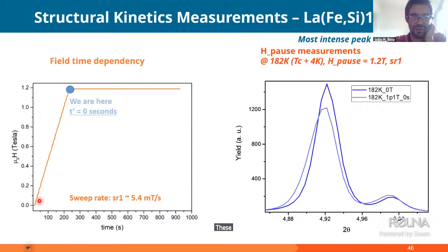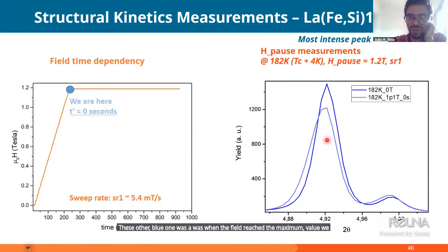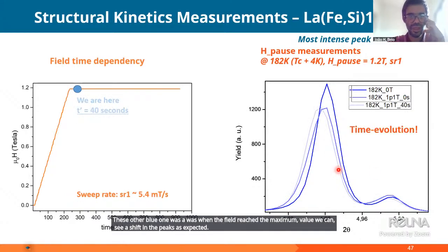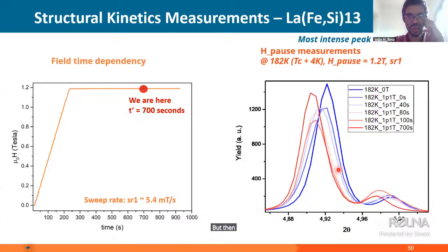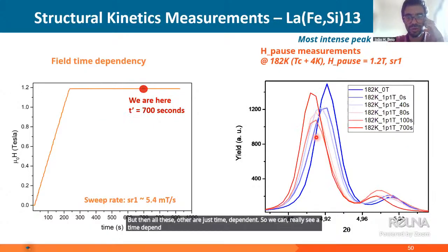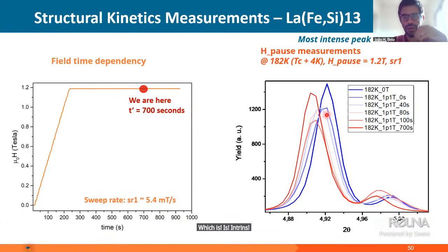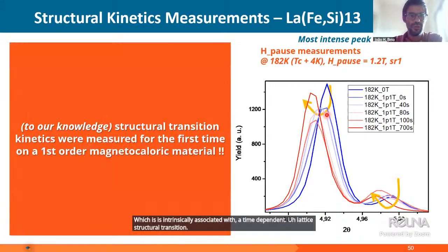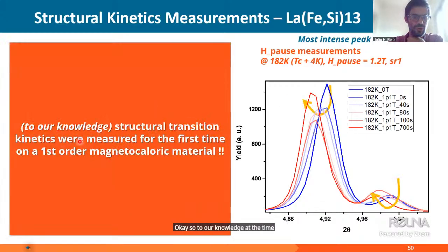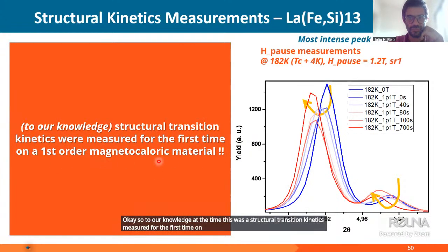This other blue one was when the field reached the maximum value. We can see a shift in the peaks, as expected. But then all these others are just time dependent. So we can really see a time dependent evolution of the XRD peaks, which is intrinsically associated with a time dependent lattice structural transition. To our knowledge at the time, this was the first time structural transition kinetics were measured on magnetocaloric materials.